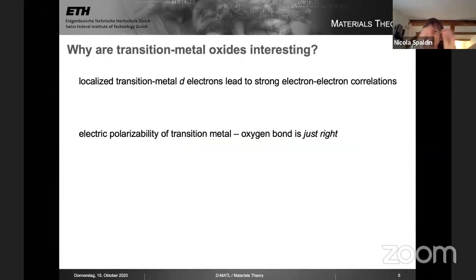But the oxygen, which is just in between, is neither strongly ionic nor strongly covalent. And so it's very susceptible to perturbations. And this combination of the two properties, the strong electron-electron correlations, leads to strong responses, in particular to magnetic fields, magnetic perturbations, and the polarizability of the oxygen bond leads to strong response to electric fields. And so this combination, transition metal sulfides or other transition metal compounds just don't have quite the richness, I'd say, of the transition metal oxides.